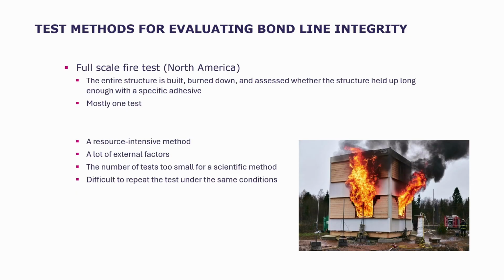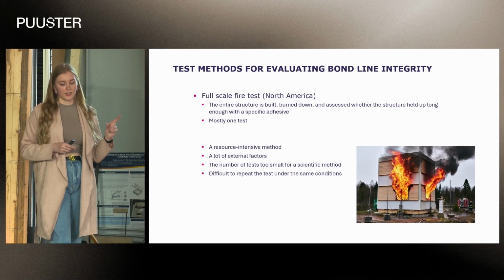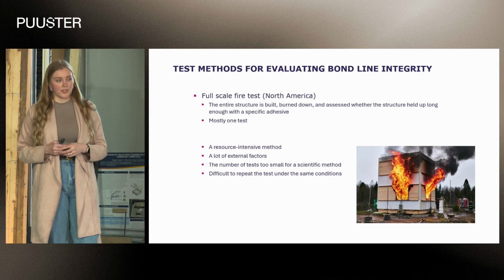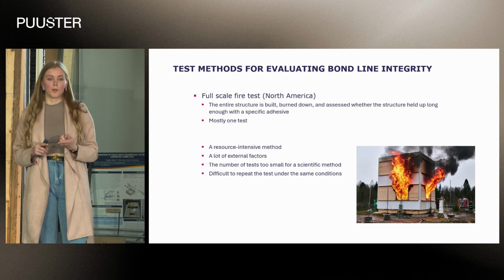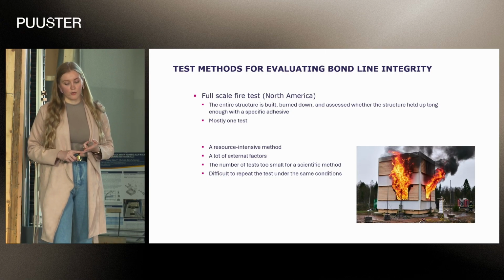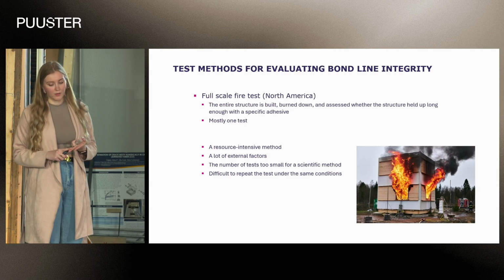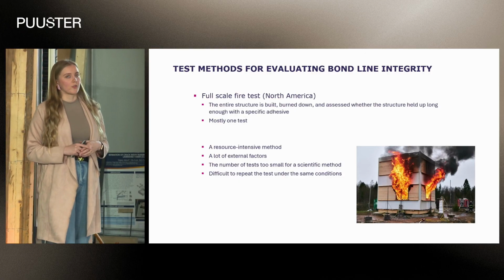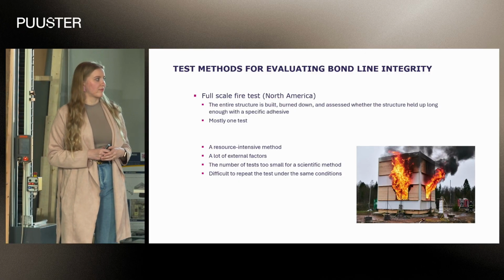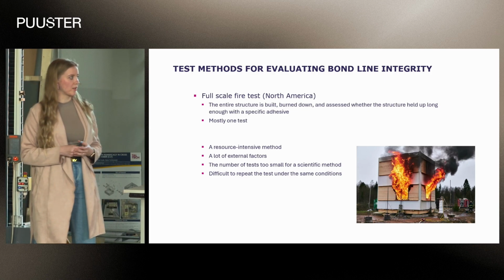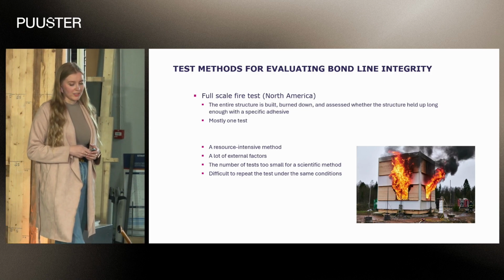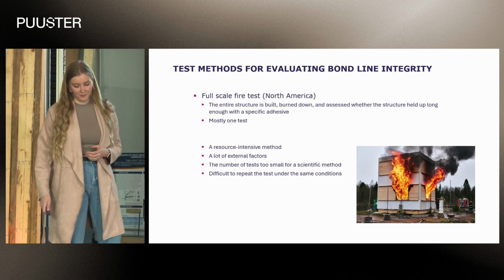It's the full-scale fire test that's mainly used in North America right now. And essentially it's just that the building is built up, the whole structure is built, it's burned down, and it's just checked whether the structure held up long enough with that specific adhesive in those specific conditions. And since it's very expensive, I would say it can go up to 6 figures, and also a resource-intensive method, mostly only one test is conducted. Also, even if we had the means to repeat the test, it would be not under the exact same conditions. So one test might not be enough for a scientific method, in my opinion.